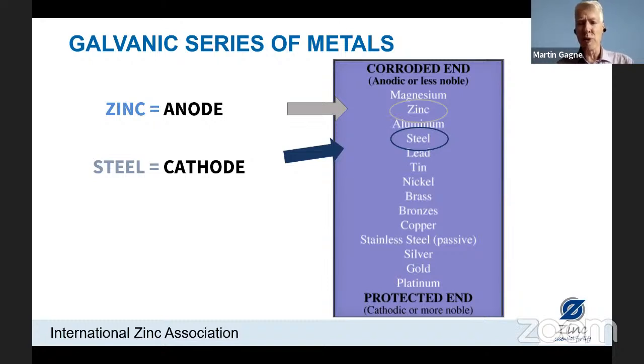Magnesium and aluminum are also above steel. These three elements are commonly used as sacrificial anodes, but there is a difference. Aluminum has about 1/10 of an electron volt difference from mild steel, so there's not much driving force there for galvanic protection, and it provides more barrier protection. We saw in the data that Simon showed magnesium has 1 full electron volt potential difference with steel. So there's quite a lot of driving force there. So magnesium is very reactive, very effective for galvanic protection, but it doesn't last very long.